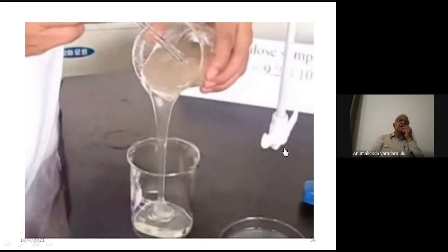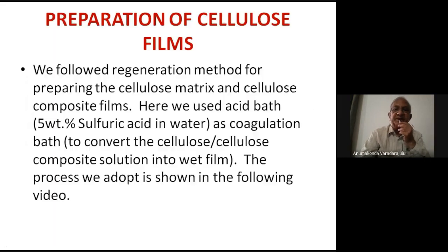Whereas with the industrial cupric solvent and carbon disulfide, it takes 24 hours for dissolution. So from 24 hours, we reduced the time to 2 minutes. So for preparation of the cellulose film, after getting that solution, suppose you want to make it as a composite, you add that material, a filler or a fiber, and then mix them together and then cast the film.